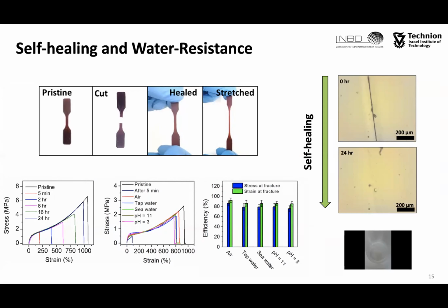Since one of our goals was to introduce superior resistance to humidity and water conditions, we tested the self-healing ability of the new polymer under different aqueous environments, including tap water, acidic seawater with pH around 3, and basic solution with pH around 11.